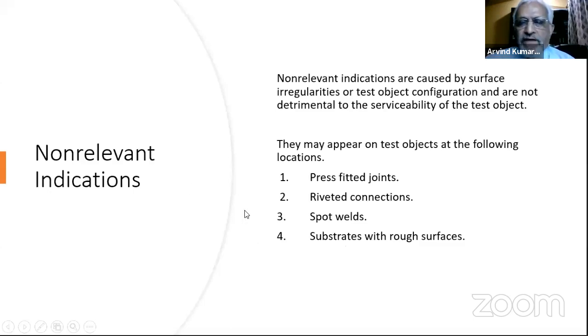A non-relevant indication is really an indication which, if you are not aware of how the manufacturing of the component is done, you may interpret as a defect, but it is non-relevant. Like press fit parts will give you an indication where the press fitting is done. There you will get an indication because it is not totally fused. Riveted connections and spot welds are some of the areas where you know that there is going to be an indication which you should be able to interpret properly, that yes, this is not the defect I'm looking for. It is a part of the component that is giving an indication.